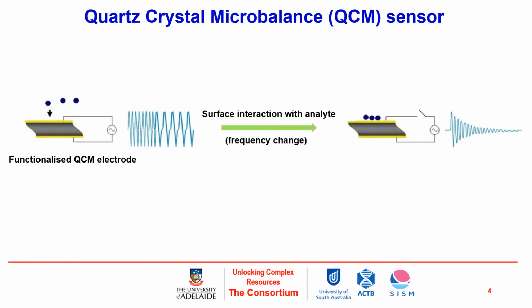To achieve real-time detection of these agents in solution, we require a system called a quartz crystal microbalance. Quartz crystal microbalances rely on an oscillating crystal that shimmies at a particular frequency and dampens when it interacts with substrates that bind to its surface. Within this project, we're aiming to make complementary materials that are able to bind to the surface and functionalize these QCMs to mediate interactions with the particular frother agents in solution and give a real-time readout as to their concentration.